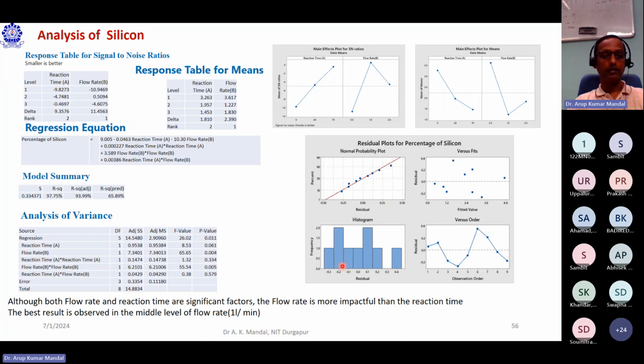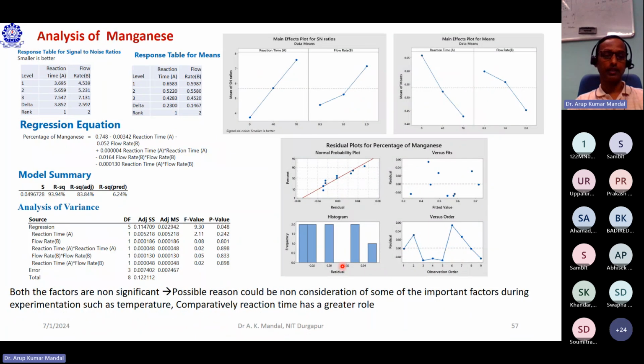Otherwise, sulfur will not react with the hydrogen. In case of silicon, although both flow rate and reaction time are significant factors, the flow rate is more impactful than the reaction time. The best result is observed at the middle level of flow rate, like 1 liter per minute in case of silicon. In case of manganese, both factors are non-significant, as I have discussed, because of the formation of a very thin slag layer, which retards the further reaction of hydrogen with the manganese. Therefore, when we go for this analysis, we see that both factors are non-significant in nature. But comparatively, the reaction time has a greater role than the flow rate here.